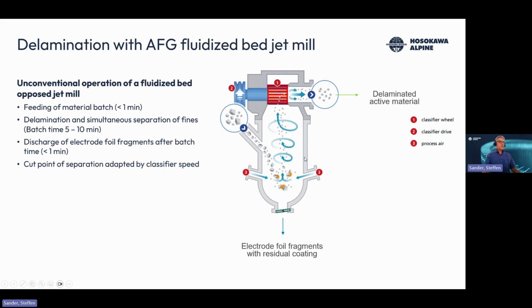The material comes into the jet mill. In this case, it's not continuously fed, but you feed a material batch, and then you stress the materials using the jets that are usually used for the comminution of the material. And during the process, the delaminated material will be discharged through the classifier. The electrode foils with the residual coating are held back inside the mill and sent back to the, let's say, stressing zone down here. And after the batch time, you can discharge the electrode fragments from the bottom.